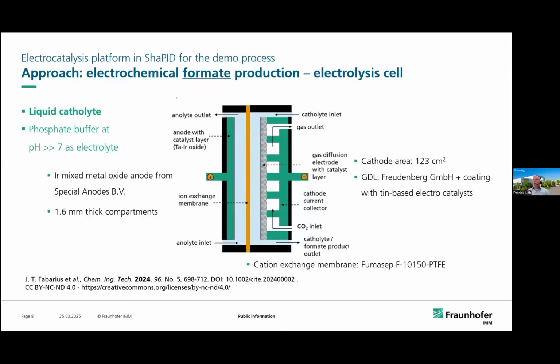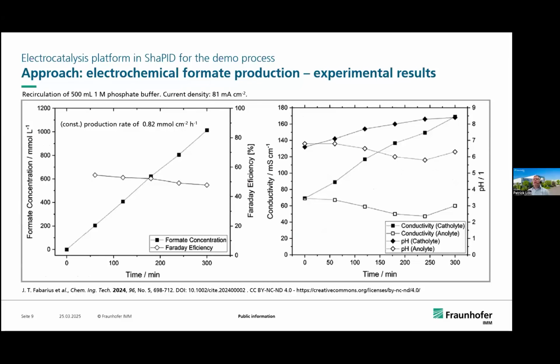So this was one process option we explored, and here you see some selected results. We reached a current density of up to 81 milliampere per square centimeter, and a molar concentration of formate of almost 1 molar as final concentration in our experiments. You see that we have quite a constant Faraday efficiency over the process time. So this was the one approach.